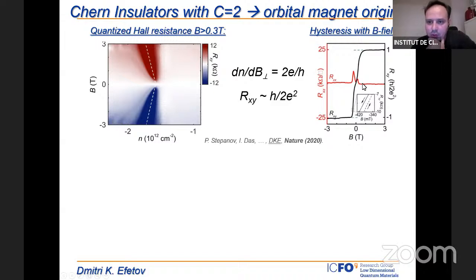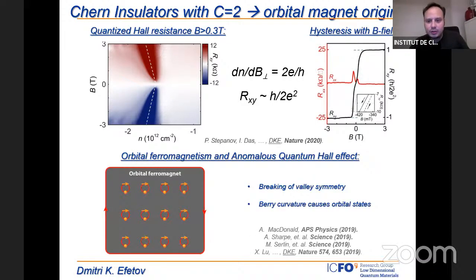So again, as expected from a quantized Hall conductance, so basically as expected from edge transport. And of course, further evidence is that this shaped region here also has a slope in magnetic field. So in the dn over dB diagram, it also has a slope consistent with a Chern number of 2. And basically, the ongoing picture, this story is now probably the fastest developing one. I haven't introduced the data in this talk, but we have a paper on arXiv which shows these features in much better detail. And then there's also the group of David Goldhaber-Gordon, the group of Andrea Young, and also Ali Yazdani had a paper recently on all those features.